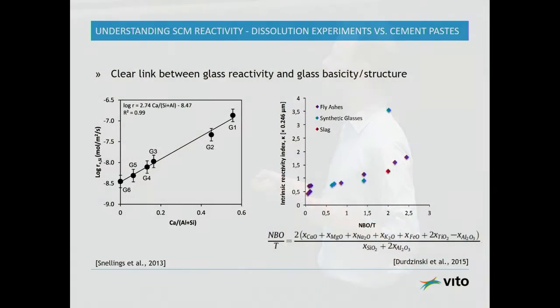So this is something we clearly found for these model systems, but you can also find this when you look at, for instance, these systems that we were characterizing in the calcareous fly ash, and we were following it through SEM analysis. Also here you see, okay, this is a different measure here. This is the non-bridging oxygen over the tetrahedral oxygens. So this is this kind of formula, but it's basically doing the same as here. And you can see there's a correlation as well, very nicely.